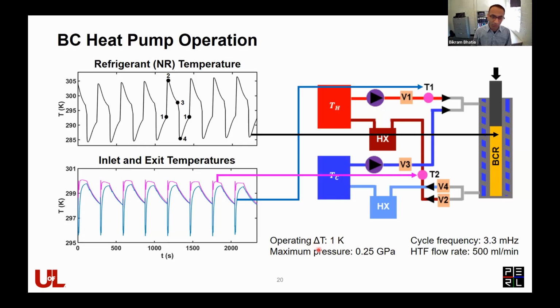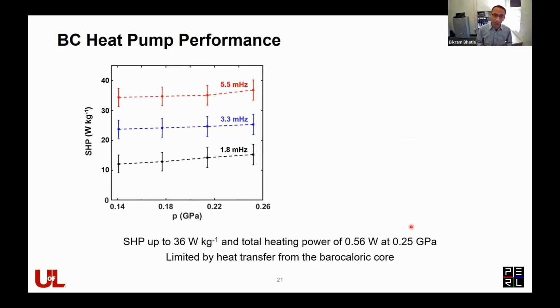So we did experiments as a function of delta T. The results that are shown here are for a delta T of 1 Kelvin, 250 megapascal applied pressure, a cycle frequency of 3.3 millihertz, and a heat transfer flow rate of 500 milliliters per minute. From this experimental time series data, we can extract the specific heating power. Like I showed before, as you apply more and more pressure, you increase the specific heating power, which is what we see for all these experimental results.